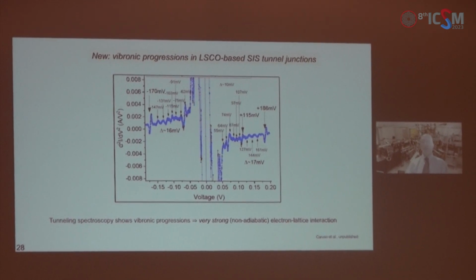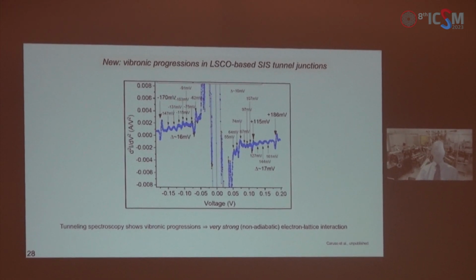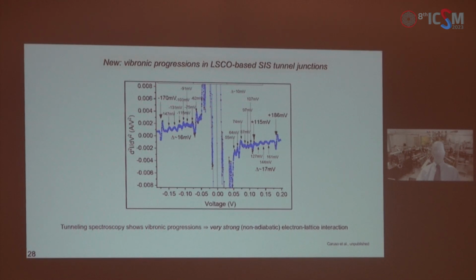So what you see here are these periodic features which are called vibronic progressions. They come from when a quasi-particle is excited above the gap, then it interacts strongly with the lattice and emits multiple acoustic phonons. Such vibronic progressions are very rarely seen, in particular with this many oscillations, and they are known as a hallmark of strong electron-lattice coupling and non-adiabatic physics.